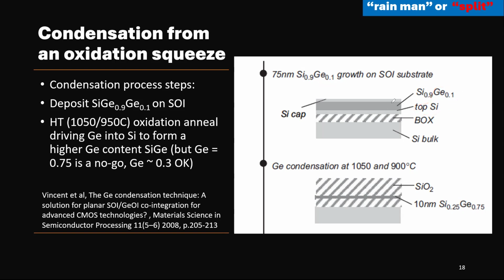So if you use a very thick layer of germanium, then you could have this new silicon layer become SiGe with a higher germanium content, whatever percentage you want to put in, right? Very high germanium content. Of course, you don't want to use it too high. Anything above 0.3 is not used. This one is just for demo. Usually we go about 30%. So you could manipulate the content of the layer here, and then you could design any germanium content layer that you want. He's a French guy, Vincent. I know him very well. When I worked at IBM in Albany, they developed this a long time ago.